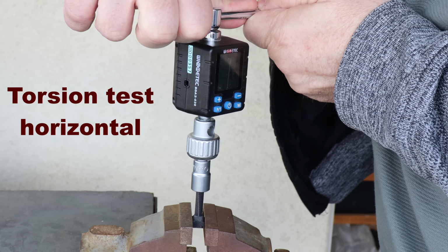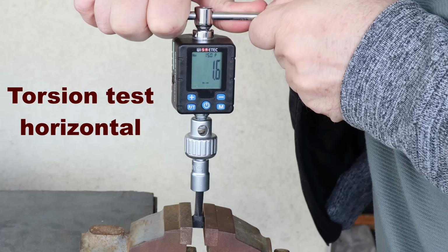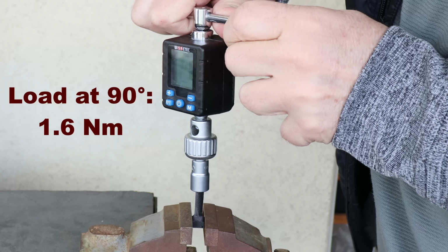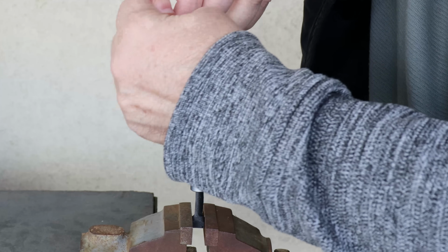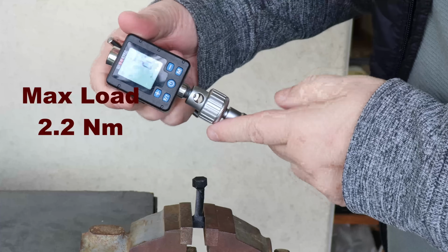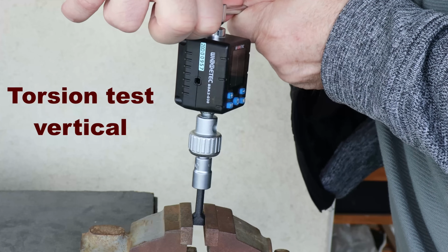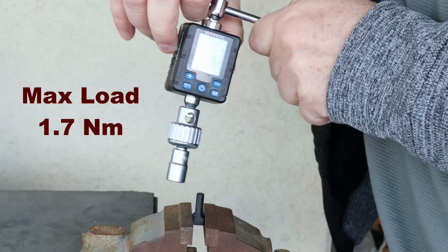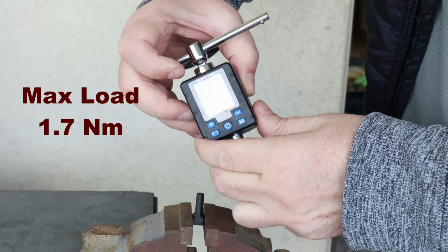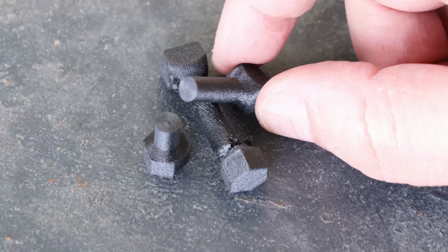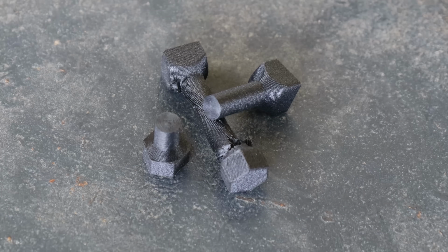Torsion test. I'm starting with the horizontal one. This is the load at 90-degree rotation. And after almost one turn, this is the maximal load. Printed in vertical position, the maximal load 1.7. As always, similar numbers but different break type.